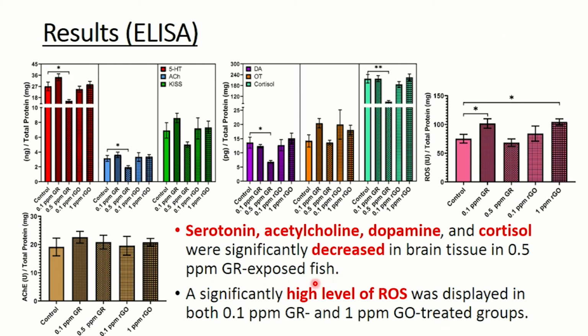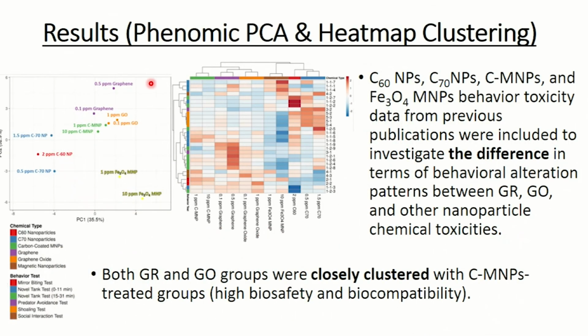On the other hand, intriguing results were found during reactive oxygen species, or ROS, measurements. From the results, a significantly high level of ROS was displayed in both 0.1 ppm graphene and 1 ppm graphene oxide treated groups. Next, to investigate the difference in terms of behavioral alteration patterns between graphene and graphene oxide, a phenomic approach was used. Thus, carbon-60 nanoparticles, carbon-70 nanoparticles, carbon-coated magnetic nanoparticles, and magnetic nanoparticles behavior toxicity data from previous publications were included to perform the heat map, hierarchical clustering, and PCA comparisons.